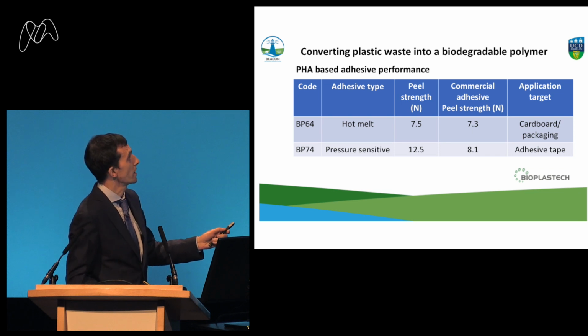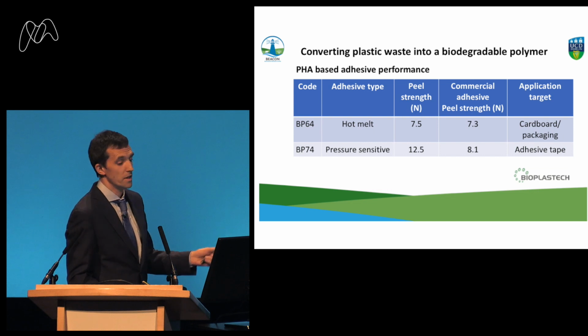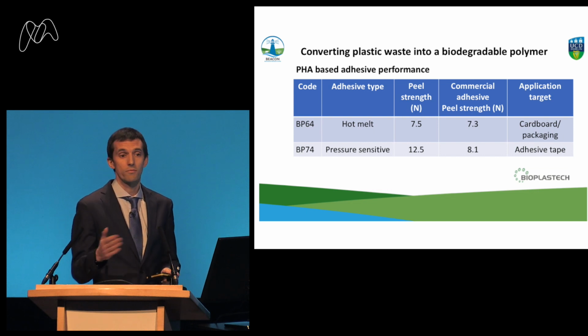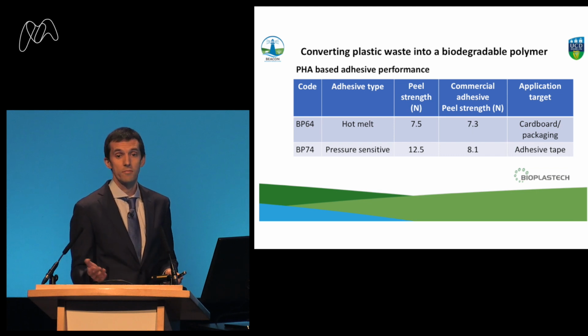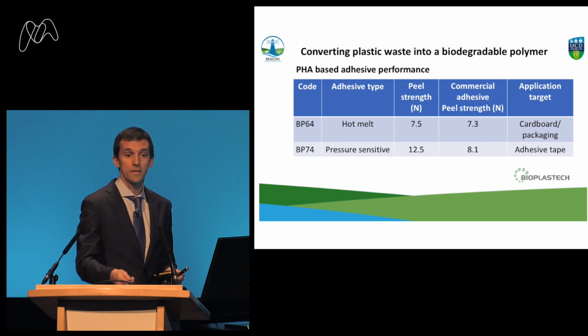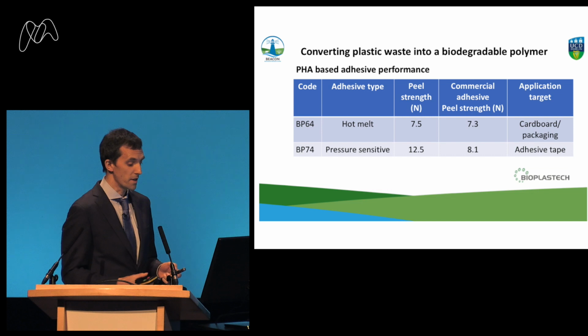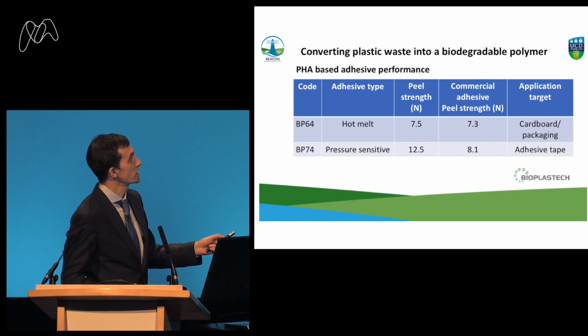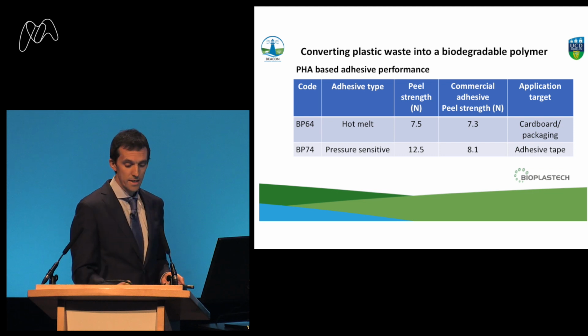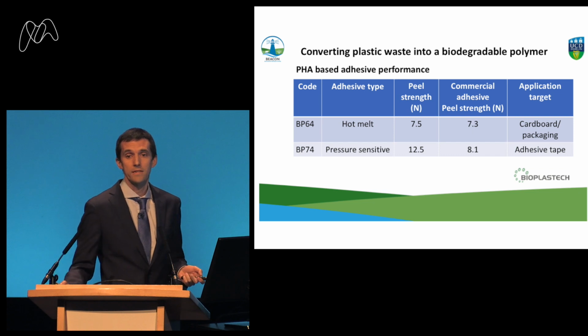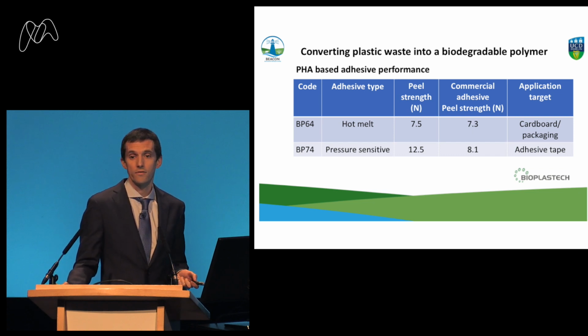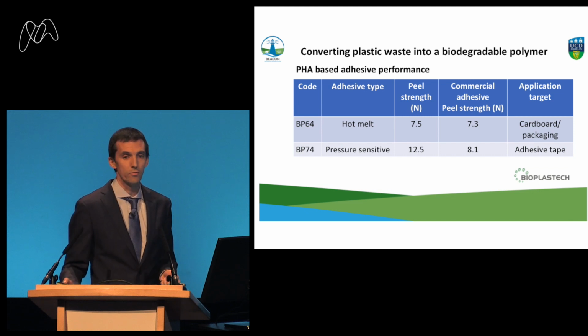We then processed the polymer in a different way to make a different product, a pressure-sensitive adhesive. One of the most famous pressure-sensitive adhesives would be the Post-it. So you can put it on, take it off, put it on, take it off. Also Scotch tape, Sellotape, they have versions of this where you stick it onto a surface and you can peel it. So we had a peelable pressure-sensitive adhesive. Its strength was around 12.5 newtons, compared well to the commercial, and we're developing an adhesive tape for that. So we can take petrochemical plastics, recycle them using a combination of chemistry and microbiology, and then develop products that can be used as biodegradable glues in the market.